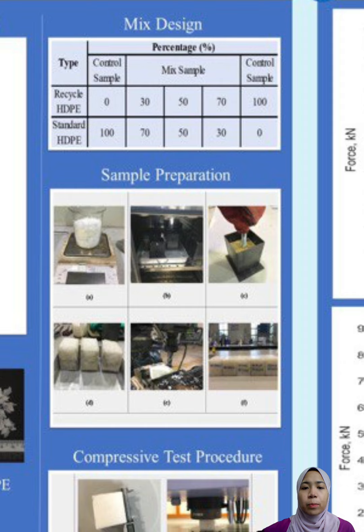For sample preparation, using an analytical balance in the laboratory, the HDPE plastic obtained from the factory is first weighed according to the mix design. Then the particles were put in the mold and heated inside the industrial oven for 1 hour at 180 degrees Celsius. After that, the plastic is removed from the oven to be compressed to avoid holes. The sample is allowed to harden for a while.